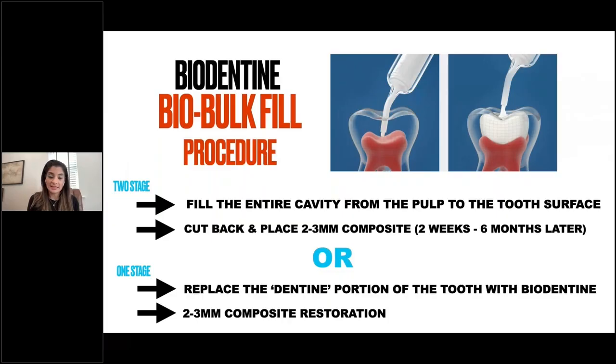And that's because Biodentine doesn't have very good wear resistance. So you do need to get them back to definitively restore the tooth, but it can last for quite a significant amount of time. And that then gives you time to analyze, how's that patient doing? Are they having any symptoms? So it gives you that flexibility.